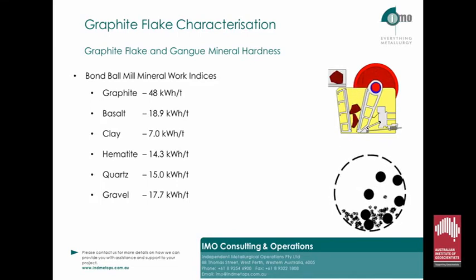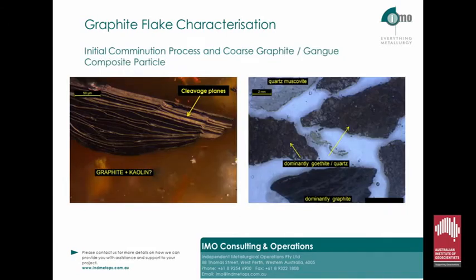In this slide you can see the Bond mill work indices of other minerals, and most of us during our lives would have had the misfortune of getting sand, primarily made of quartz, in our mouths and trying to break the sand with our teeth, which is not easy. So whilst graphite is hard, like all minerals, it will break if too much energy is imparted on it. In this picture you can see discrete graphite and gangue layers, which will act as cleavage planes, which should allow the graphite to liberate from the gangue during the initial crush and grind process.